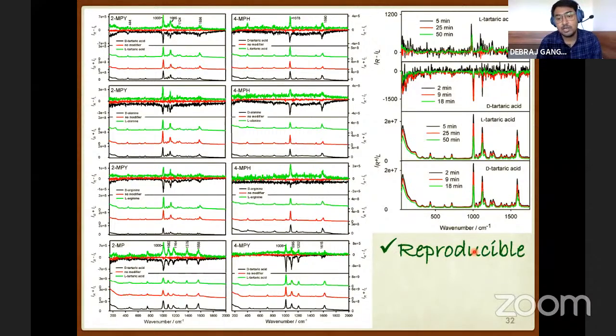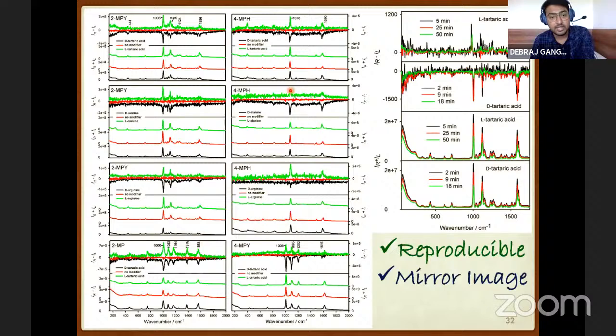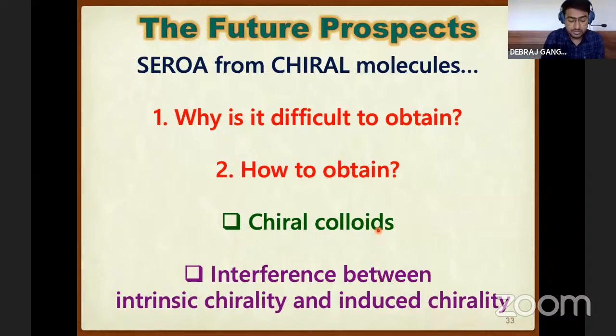Experimentally, we have produced reproducible Raman optical activity spectra. We have seen that there's a mirror image of the two enantiomers, the D and L form. And the third aspect that we have discovered is that the CID is also in the range of 10⁻³, which is very much acceptable for surface enhanced Raman optical activity. So this was what we did. And as future prospects, the work that I have discovered now is that we have shown experimentally reproducible surface enhanced Raman optical activity, or we have combined the two spectroscopic techniques, surface enhanced Raman scattering and Raman optical activity, into one, and we have successfully produced reproducible spectra.